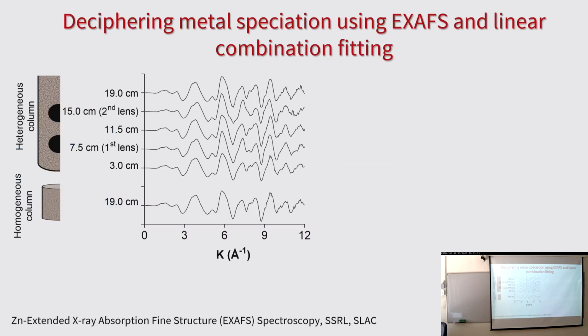So for that, we performed zinc extended X-ray absorption fine structure spectroscopy, or in short, XAFS. XAFS is a really powerful tool to learn about the oxidation state of a metal as well as its surrounding chemical environment. After collecting the data, you get these squiggly lines, and then we employed linear combination fitting in order to learn about the species distribution of zinc within our sample. In linear combination fitting, essentially you use a set of reference compounds, and try different combinations of those compounds to reconstruct your experimental data.